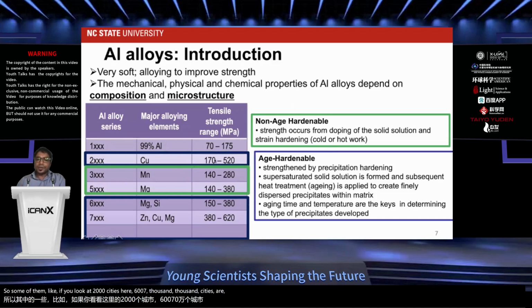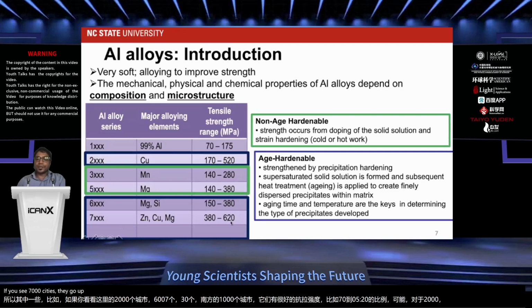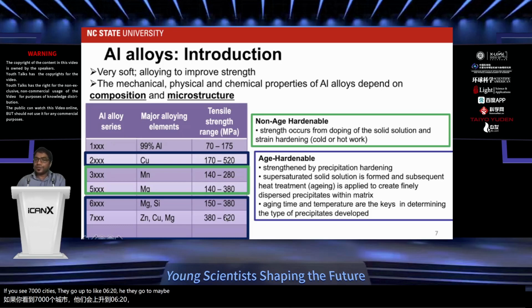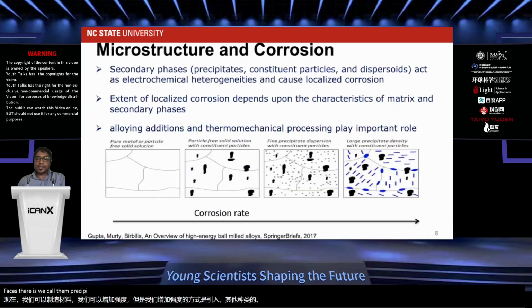Some of them, like the 2000 series here, 6000 and 7000 series, have pretty good tensile strength, like 170 to 520 megapascal for 2000. The 7000 series go up to 620 written here, maybe 650, 660 megapascal of yield strength. Now we can make the materials and increase the strength, but the way we increase the strength is by introducing other phases there, which we call precipitates, and let's see how they impact the corrosion properties.